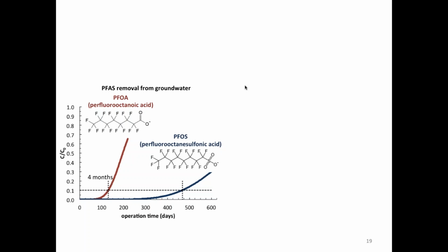The point here is that when you're considering how these systems operate, you have to take into account not only the target compound that you're interested in, but also the background water matrix, which has a huge influence on how adsorption takes place. Some compounds adsorb much more strongly than others. For example, PFOS adsorbs much more strongly than PFOA. So there are a lot of factors to think about.